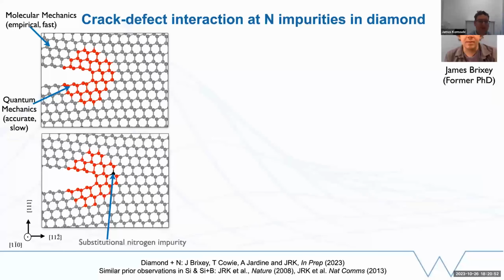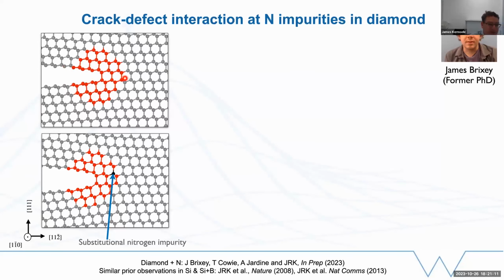One more example application on this front. This is work from a former PhD student who's just finished recently in my group, James Brixey, looking at interactions between cracks and defects. So this is in diamond rather than silicon. Now we have a diamond matrix, and the relevant defect is nitrogen impurities. So let's look first at the pure diamond case at the top. So we're looking here at fracture of diamond on the 1-1-1 plane. We see, similar to silicon, bonds breaking one by one, and the crack is propagating forwards. No reconstruction of the fracture surface in this case, so it's a simpler process. Bonds are breaking, crack is moving forward.